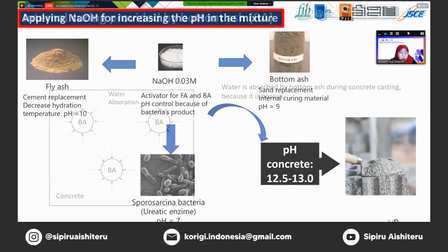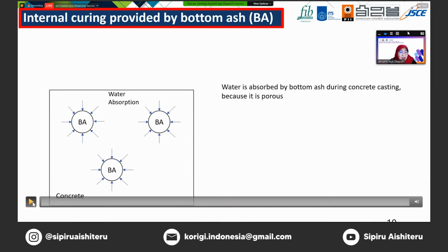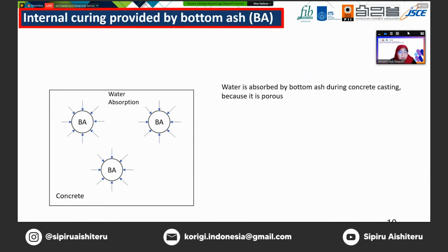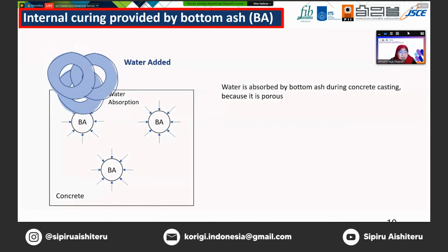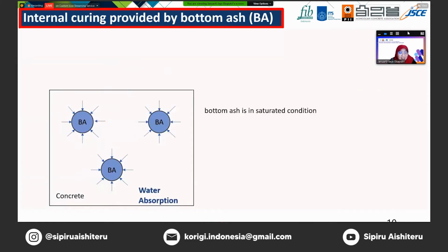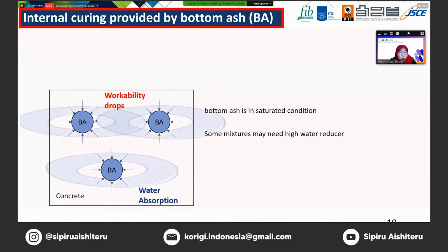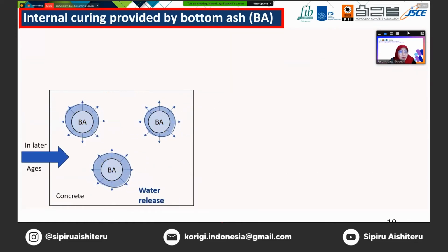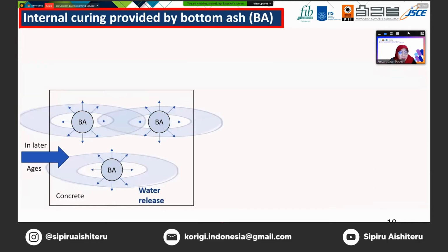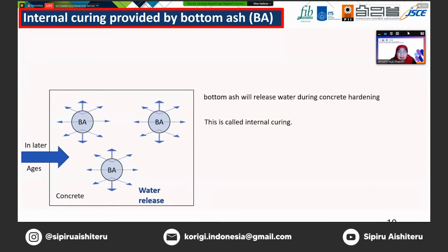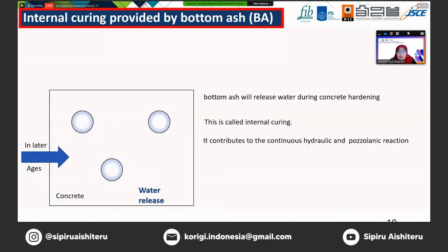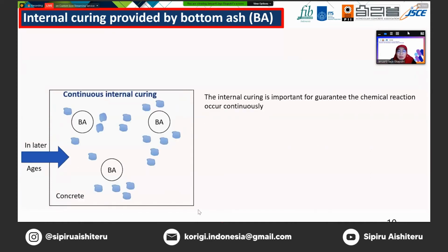And I have also the schematic simulations. This is the internal curing effect from bottom ash that we expect to occur during the hydration of the concrete. It works as a sponge. It absorbs water at the beginning to lower the water to cement ratio and maybe lower the workability. But then it releases moisture gradually at the later age. This is called internal curing. So it contributes the moisture to guarantee the next chemical reactions, the pozzolanic reaction and the